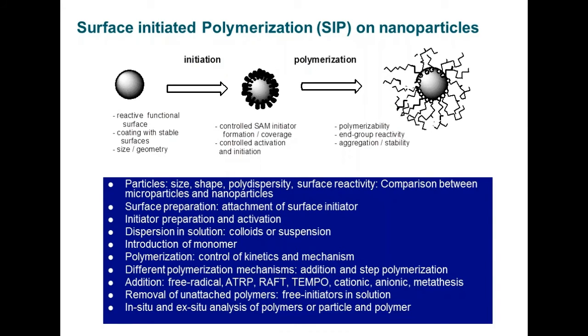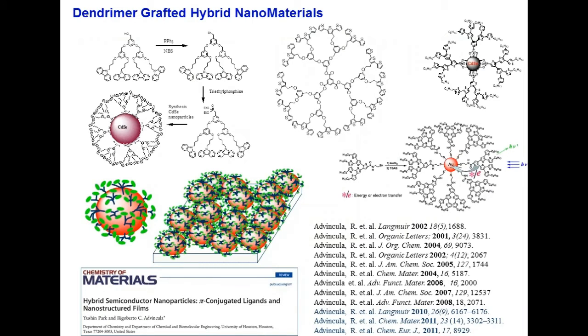properties. Another way is that we can graft polymers directly on particle surfaces as a dendritic system. As shown here, through a rational design and synthesis of electroactive monomers that then can be grafted on gold or cadmium selenide or different types of nanoparticles, which are very interesting materials by themselves, we can control the energy transfer, charge transfer, or even fluorescent materials of this size, aspect ratio, a high surface to volume ratio materials, such that they can be used for sensing or different